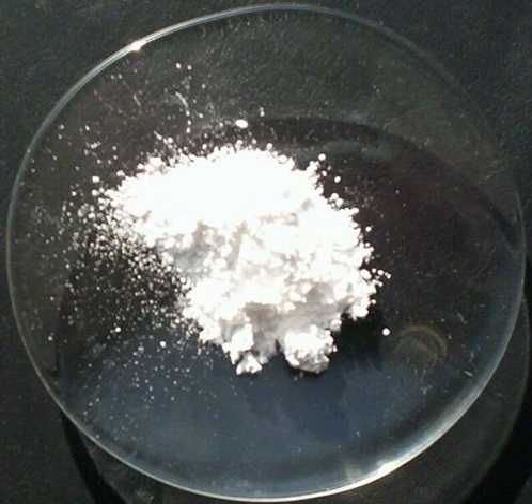High temperatures, 1500 to 2000 degrees Celsius, diminish the available surface area and produce dead burned magnesia, an unreactive form used as a refractory. Calcining temperatures of 1000 to 1500 degrees Celsius produce hard burned magnesia, which has limited reactivity, and calcining at lower temperatures, 700 to 1000 degrees Celsius, produces light burned magnesia, a reactive form also known as caustic calcined magnesia. Although some decomposition of the carbonate to oxide occurs at temperatures below 700 degrees Celsius, the resulting material appears to reabsorb carbon dioxide from the air.